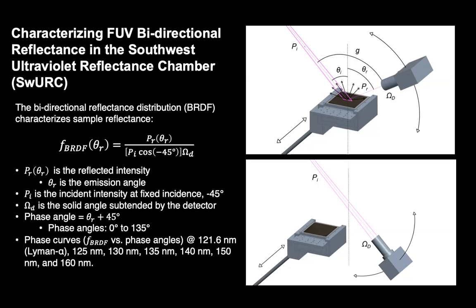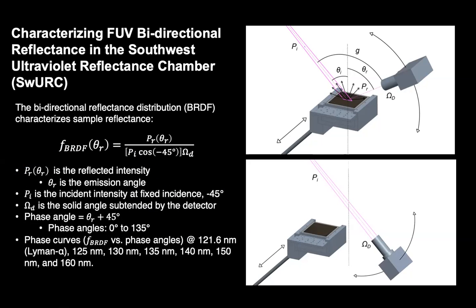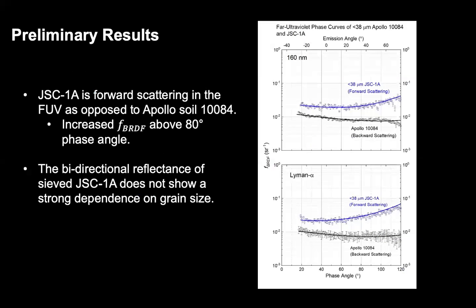For this study, phase curves, in other words, the actual plot of the intensity as a function of the phase angle, or of the BRDF, I should say, that ratio as a function of the phase angle, were obtained for 121.6 nanometers, in other words, Lyman alpha reflected radiation, 125 nanometers, 130, 135, 140, 150, and 160 nanometers. So spanning both that far FUV range and that longer FUV range.